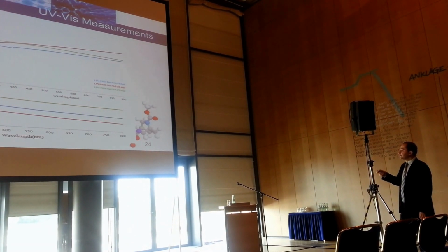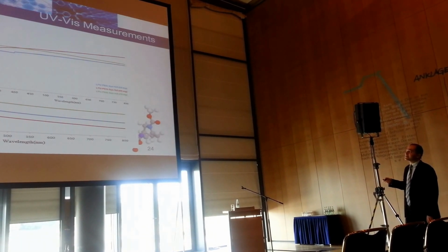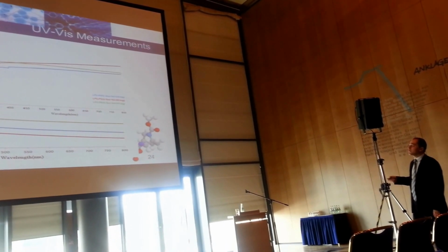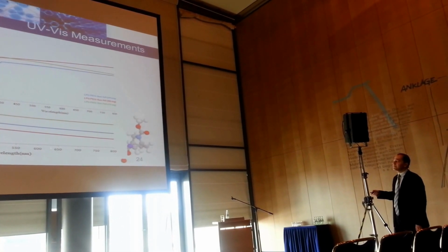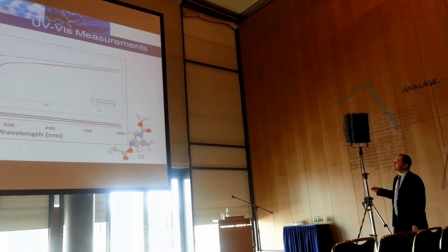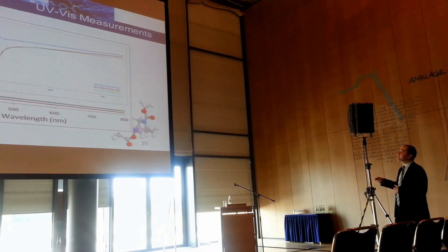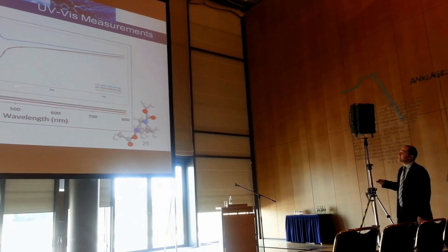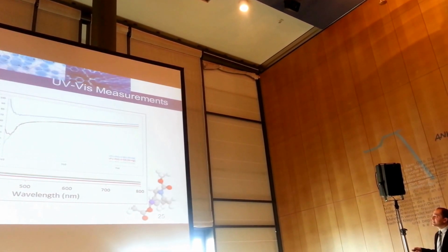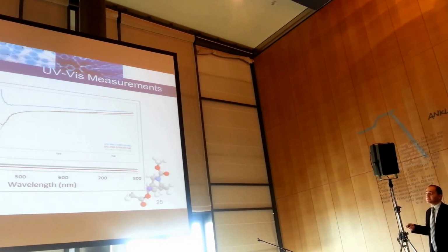For the sucrose-based polyurethane we synthesized, you can also say that the transmittance is higher than 60%, and for absorbance, above the 400 nanometer wavelength we cannot see any kind of peak. For the starch polysaccharide, we used different amounts, as we did for the previous ones: 25, 50, 75. As you can see from the image, it is also transmitting, but in the absorbance after 400 especially, we cannot see any kind of peak, so we can say that it is not absorbing, it is transmitting.